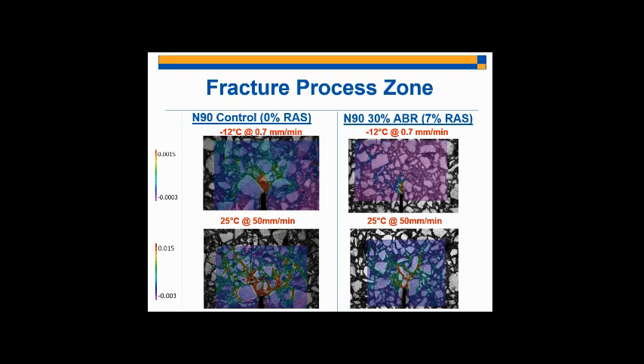And so you can see that what happens is, as you add recycled content to the mixture, as you add the 7% RAS, you are essentially embrittling the material. This is without a doubt. And this is proven by basically the localization of the fracture process zone. You can see here that as compared to the control mix, the 7% RAS mix displays a much more localized fracture process zone. And this is true for both -12 degrees Celsius and 25 degrees Celsius.